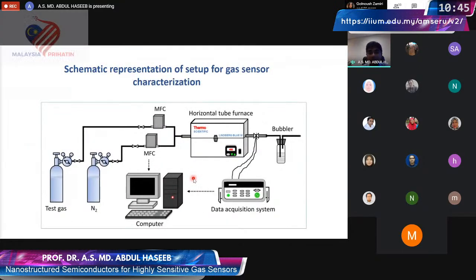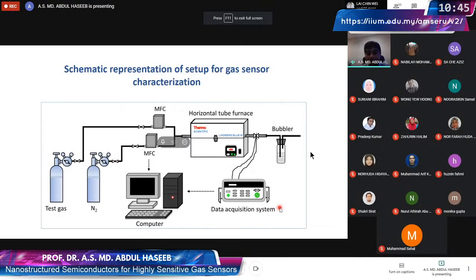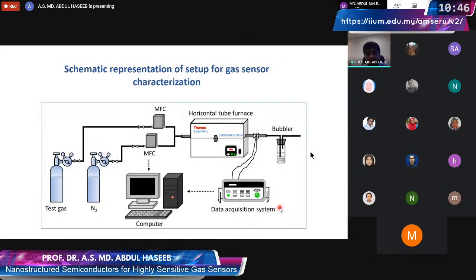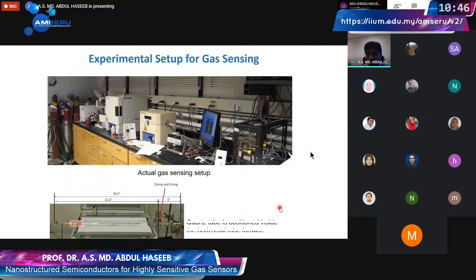And once we prepared the sensor, we put it inside a tube furnace where we can control the temperature. We also control the gas flow by accurate mass flow controller. And we can go down to about 20 ppm in our system now. And we record the data during this whole process, where we introduce different gases, and we see the variation of resistance as a function of time. And this is the actual setup. So this is the furnace, and these are the gas flow system, etc.